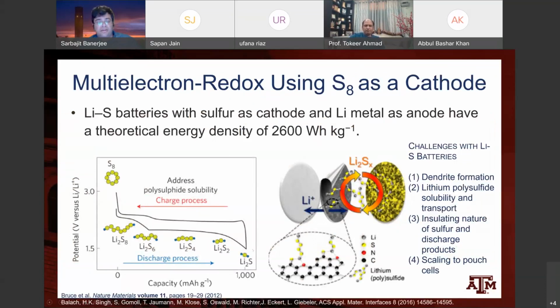Now these two products are fine, but they're solid, insoluble products. These are soluble products, and this is a problem. So like I mentioned, sulfur directly cannot be used as a cathode. Neither sulfur nor any of these products are electrically conductive. So you have to pair these with some sort of a conductive host, typically some sort of a carbon material. And then what typically ends up happening is that these products, being soluble, come out of the host and will even go across the separator and deposit on the lithium metal anode. And this can be a major problem.